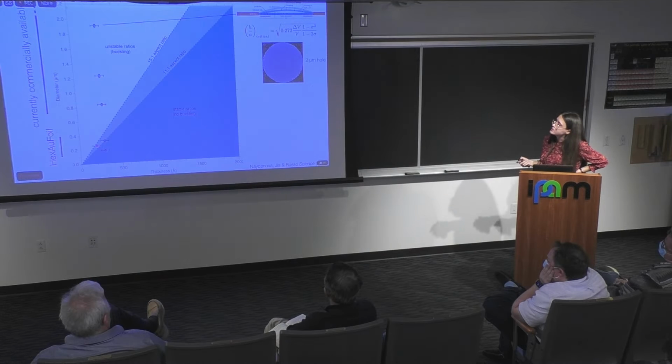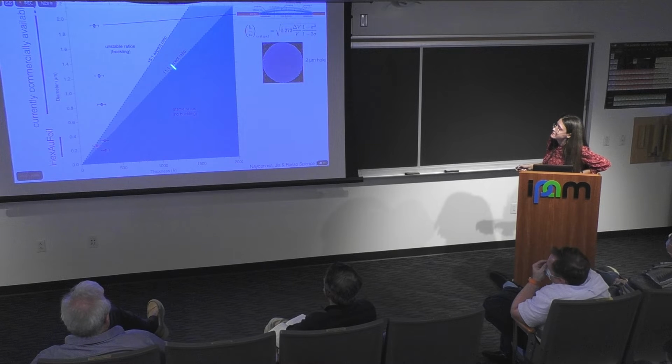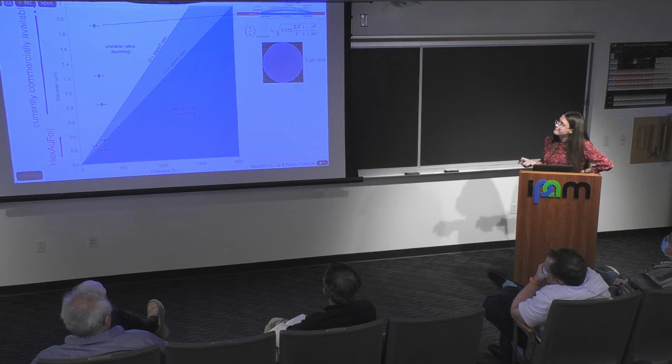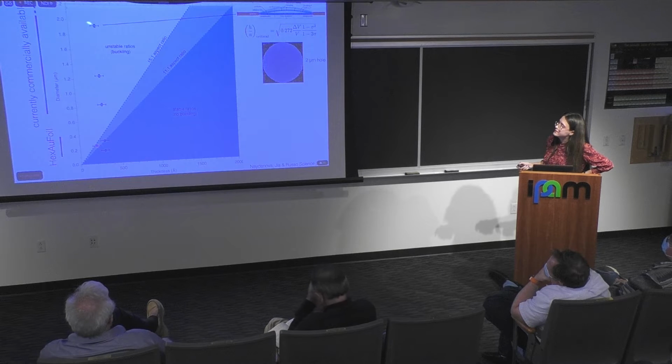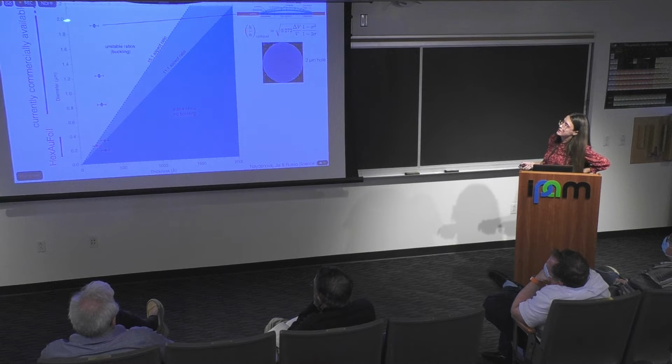If we plug in all the numbers, depending on some assumptions we make, the ratio of the optimal diameter to thickness is something between 15:1 and 11:1, meaning if we have our standard cryo-EM specimen support we're used to, something like a 2-micron hole spanned by 300 angstrom thick ice, the ratio is almost 100:1. This is not stable.